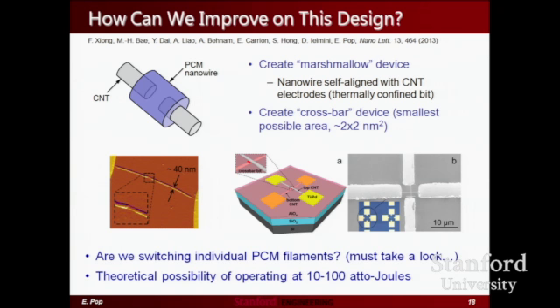We're making crossbar devices. So we're taking carbon nanotubes and we're putting them like this, like crossbars, and making the memory bit at the intersection of the two nanotubes. And that little intersection is probably an area of about 2 by 2 square nanometers, or 4 square nanometers, I guess, if you do the math, right? Which is about as small of a memory bit that you could probably make. Again, if you have a better idea, please contact me and we'll try to look into it.